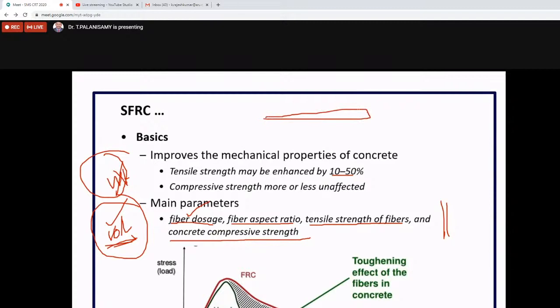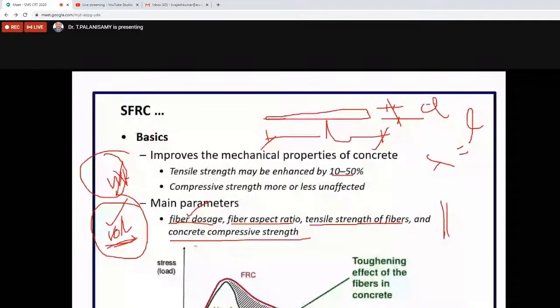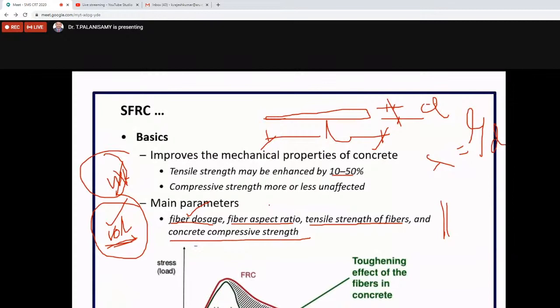Suppose I take this as my fiber. The diameter is D. The length is L. So L by D is the aspect ratio of the fiber. This is also important. If the L by D ratio is very low, what will happen? It does not control the macro cracks, since the fiber length is very small. It improves the fresh properties or rheological properties of the concrete, especially for shrinkage, creep, and plastic shrinkage. If the fiber is very lengthy in nature, it controls macro cracks. If the length is too great, segregation can occur, which also creates a lot of problems. So fiber dosage and fiber aspect ratio are very important factors.